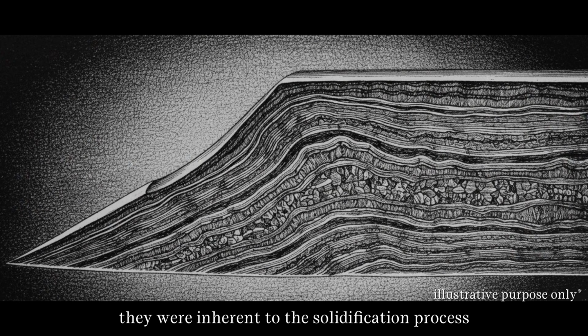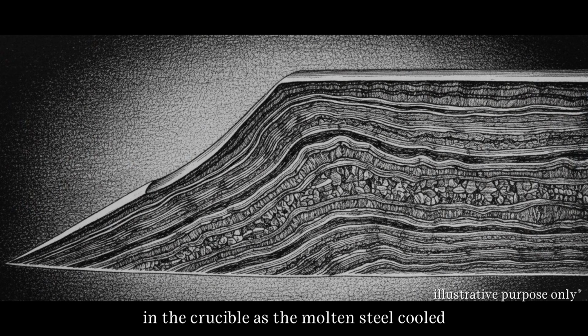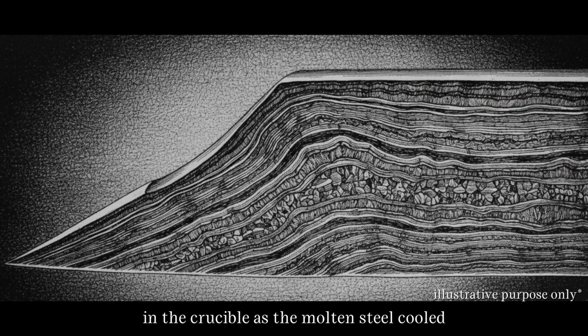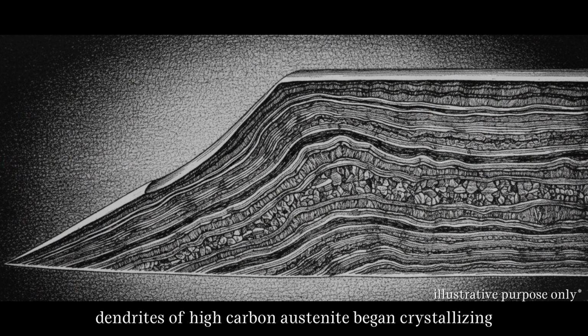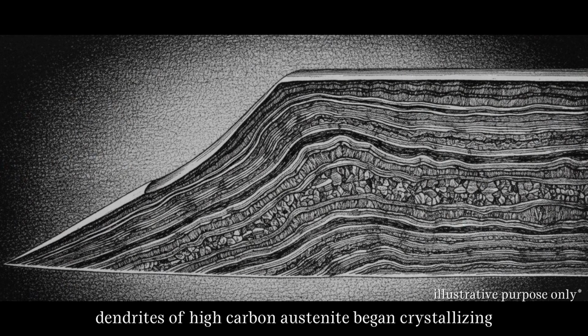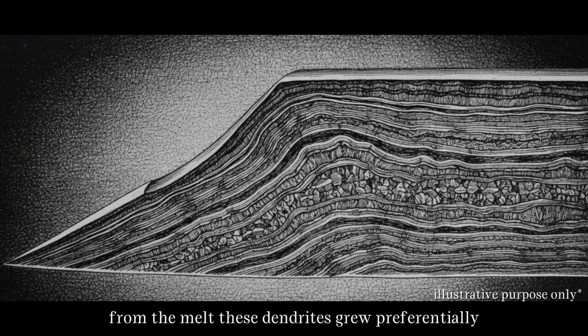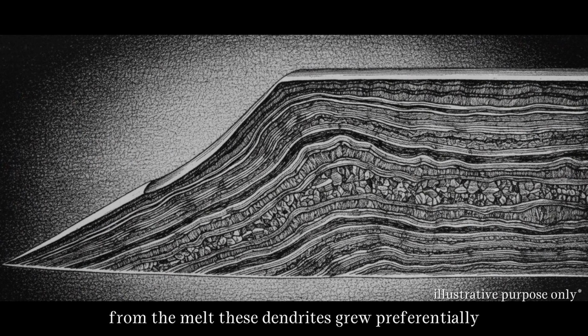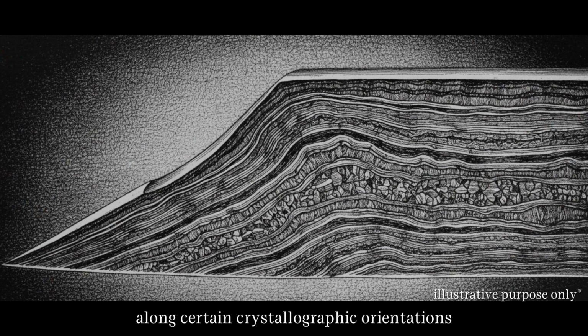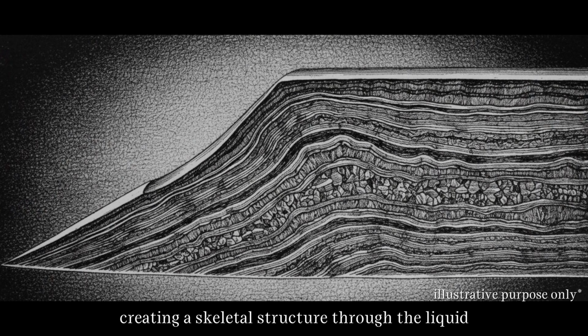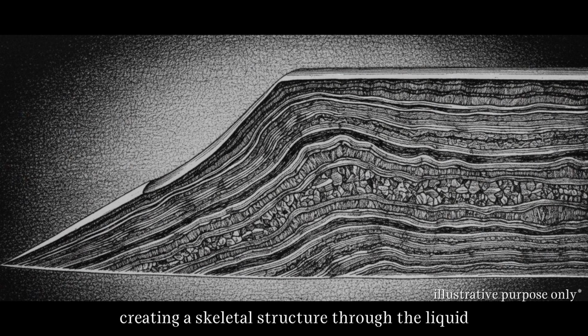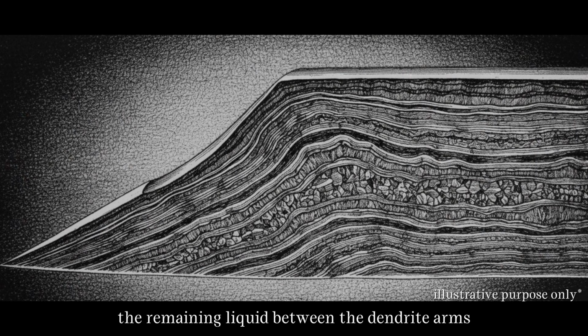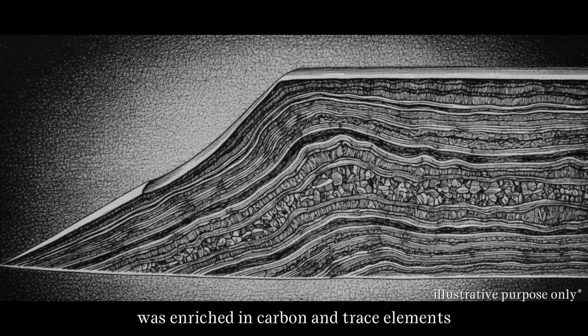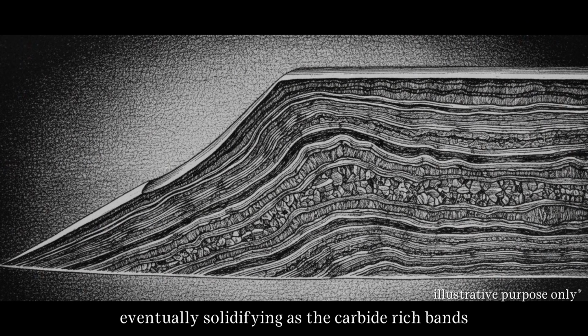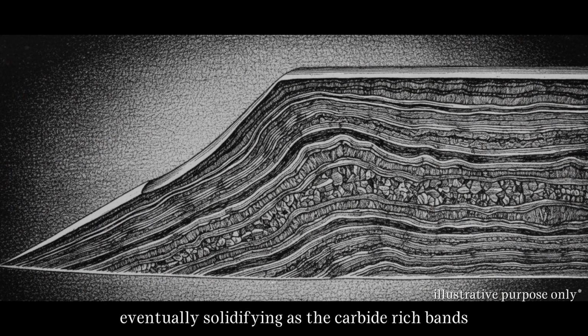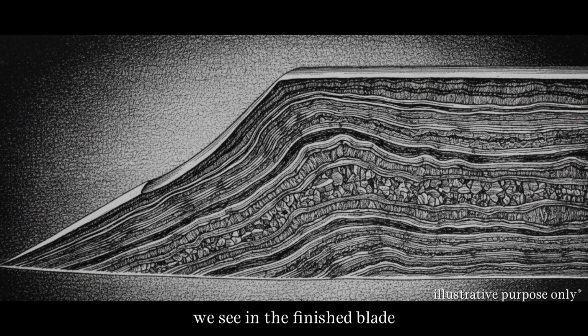They were inherent to the solidification process in the crucible. As the molten steel cooled, dendrites of high-carbon austenite began crystallizing from the melt. These dendrites grew preferentially along certain crystallographic orientations, creating a skeletal structure through the liquid. The remaining liquid between the dendrite arms was enriched in carbon and trace elements, eventually solidifying as the carbide-rich bands we see in the finished blade.